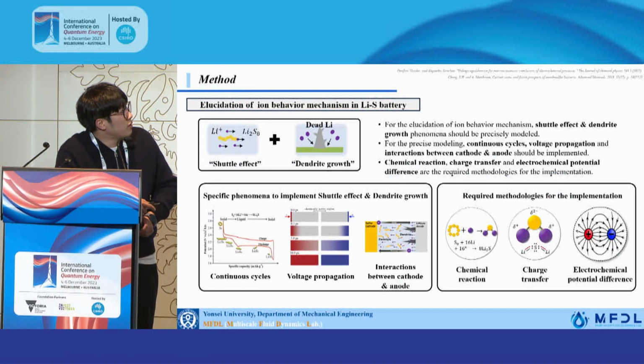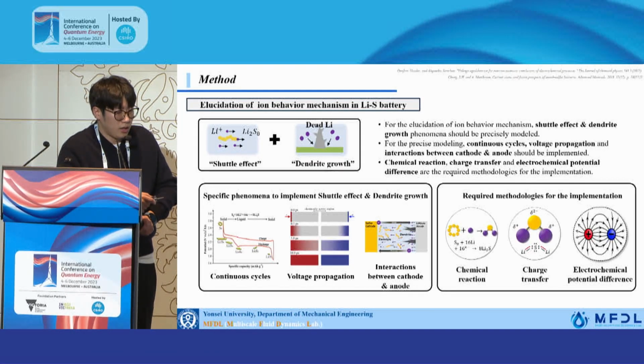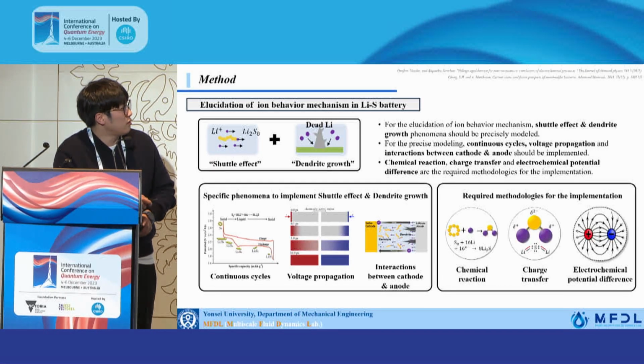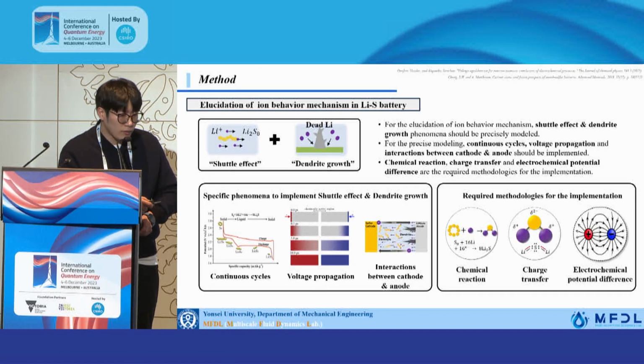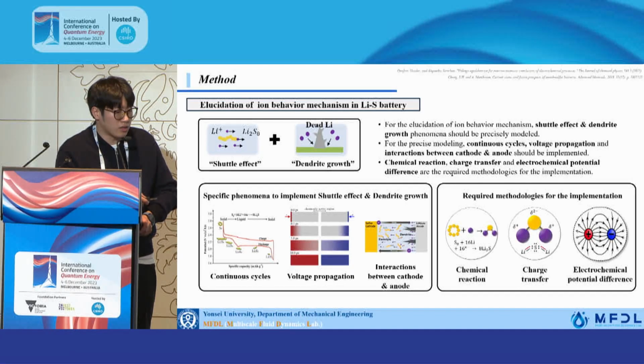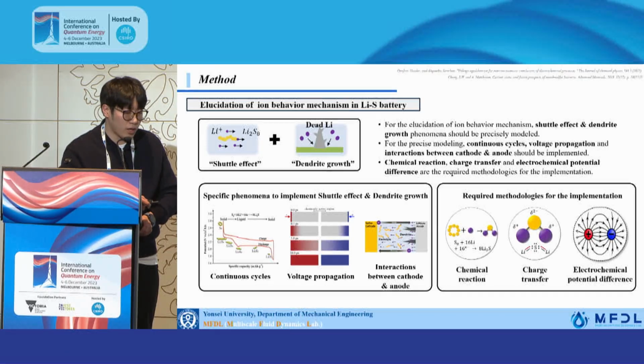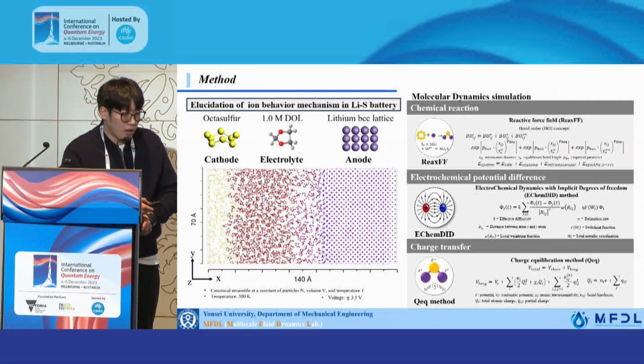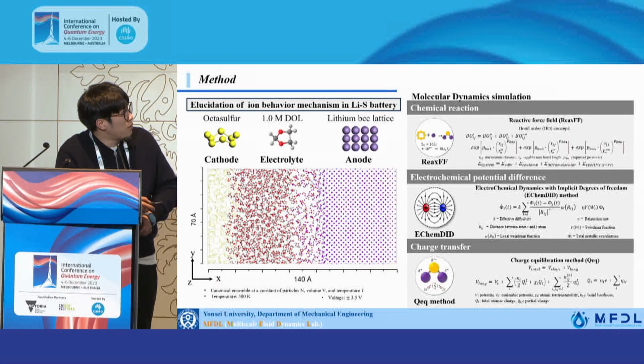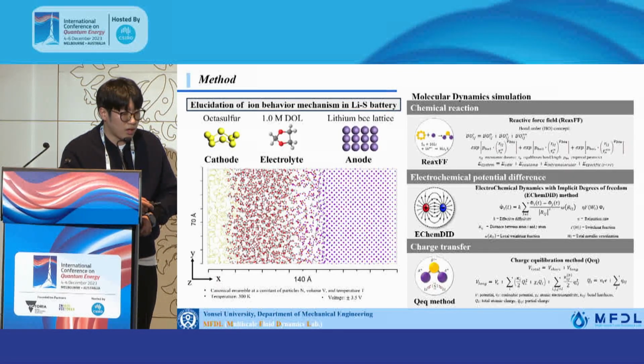So for the elucidation of the ion behavior mechanism, Shuttle effect and dendrite growth phenomena should be precisely modeled. And for the precise modeling, the continuous cycles and voltage propagation and interactions between the cathode and anode should be implemented. And for this implementation, the chemical reaction, charge transfer and electrochemical potential difference should be precisely modeled. For this modeling, we combine three main methods in the molecular dynamics simulation.